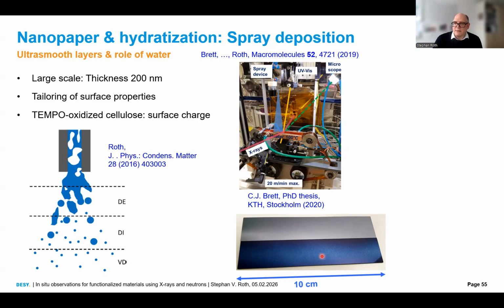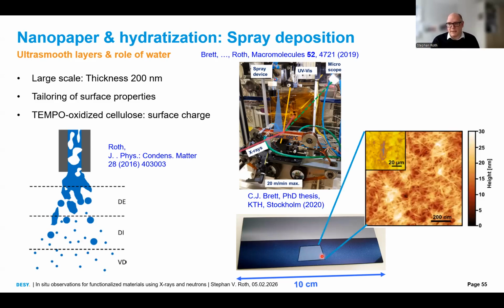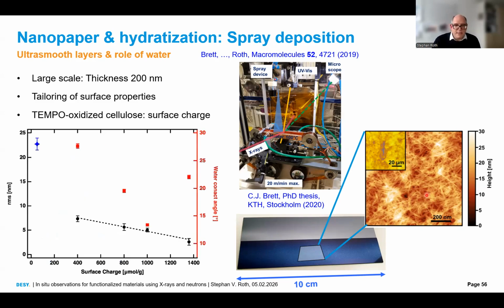This is large scale, really large scale, because DFG, German Science Foundation, states that 1 by 1 centimeter squared is large scale, and we are 20 times larger. And this is, as I said, these tiny cellulose nanofibrils in water sprayed on the surface. And this is then how it looks like in an optical microscope and in an AFM. You see here these fibrillar-like structures, you see here voids. And our question was, what do we see actually?